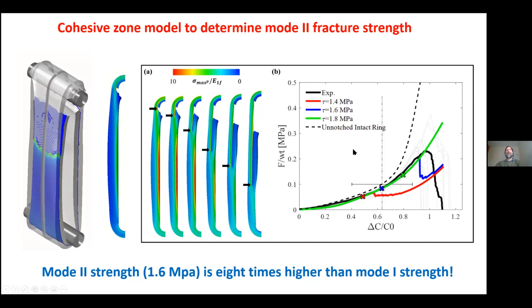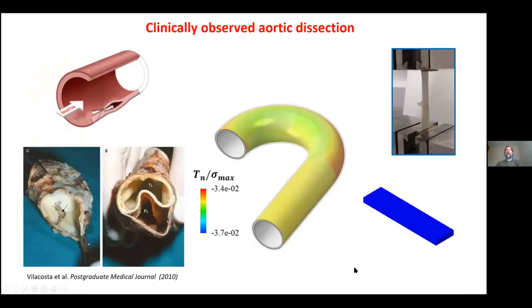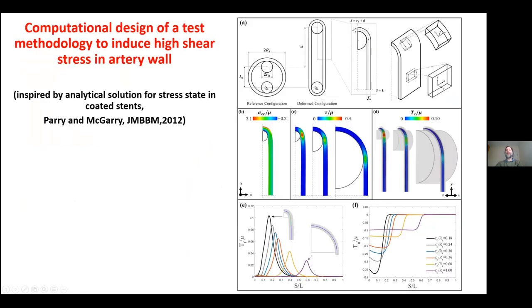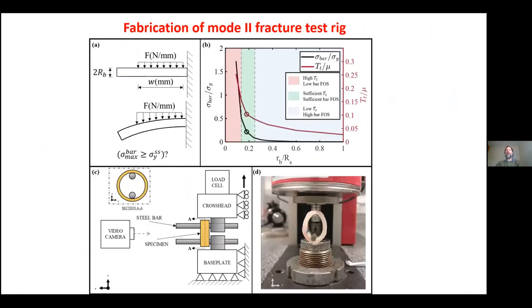And what we found is that the shear strength is about 1.6 megapascals. And this is in fact 8 times higher than the strength that you get from a peel test. So this test that everybody else is doing, which is the wrong test, is saying that the artery is 8 times weaker than it really is. Because the true strength is the shear strength. That's the only strength that matters in this situation. And it's incredibly strong.